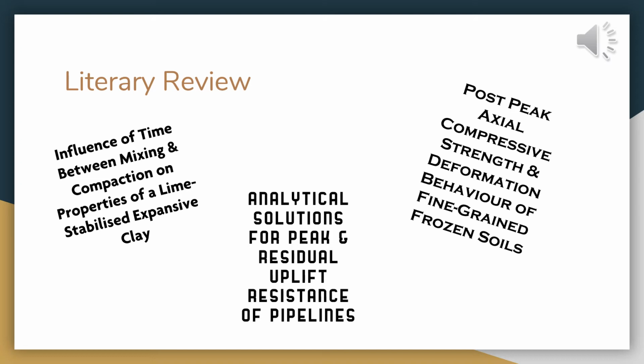Prior to the research, it was accepted that the soil with the lime stabilizer was not time-reliant when measuring its properties. However, it was found that for lime-stabilized expansive clay, the time delay between mixing and compaction had a negative effect on the strength of the soil, falling by roughly 30%, along with other soil properties. The delay measured for this was 24 hours.